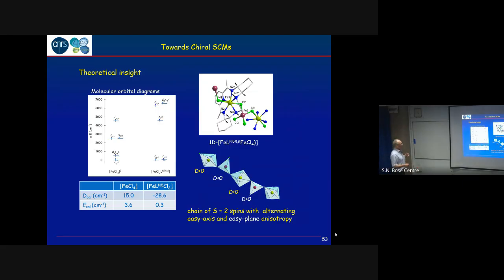So for this system, since we had the two irons in some geometry for which we expect some magnetic anisotropy, we look at the magnetic anisotropy through calculations. And this is a result of the calculation. For the tetrahedral iron, the anisotropy is positive, of the order of 15 wave numbers, whereas in the seven-coordinated iron center, we have an anisotropy that is, as expected, negative, but very large, almost minus 30.